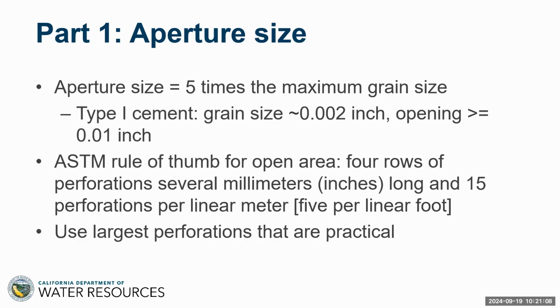And so that would be at the lower end, Julie, and that would be a thickness or an aperture, which if it were finer, would not be able to transmit cement grout. And then the ASTM rule of thumb is quite fine with me. I think that makes a lot of sense. I've got no basis to challenge that at all. But the bottom line for me is just use the largest perforations that are practical. So if that's with the Mills knife and so on, or standard PVCs or whatever, just use the biggest perforations you can reliably and economically handle, because that's going to allow you to pump quicker and pump faster, and might be a little bit more forgiving in terms of the homogeneity of the grout.